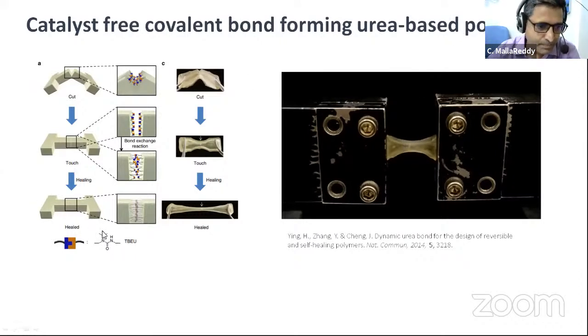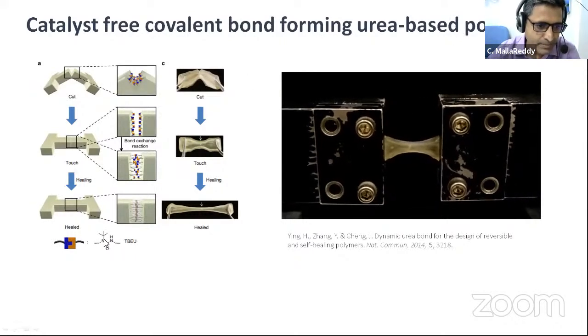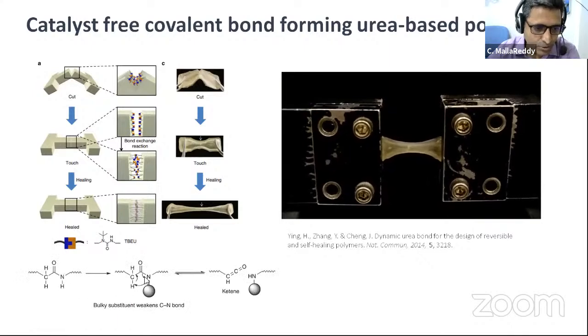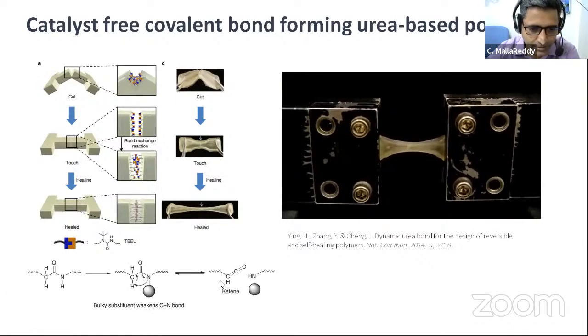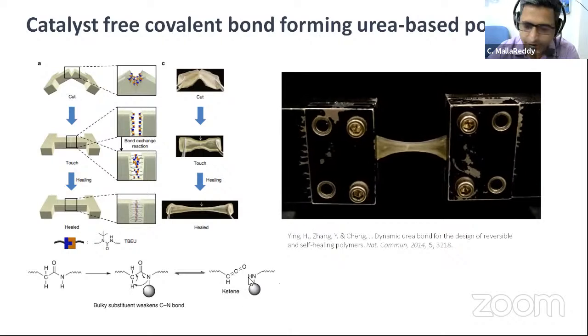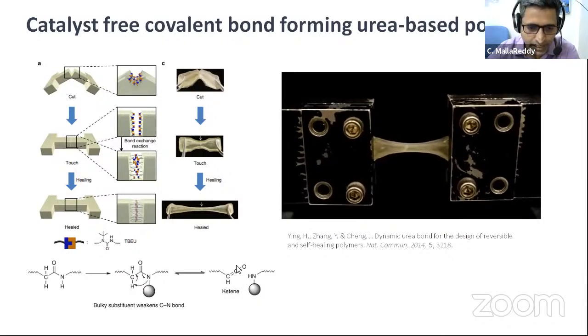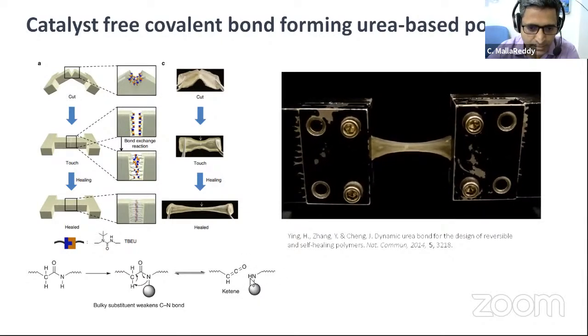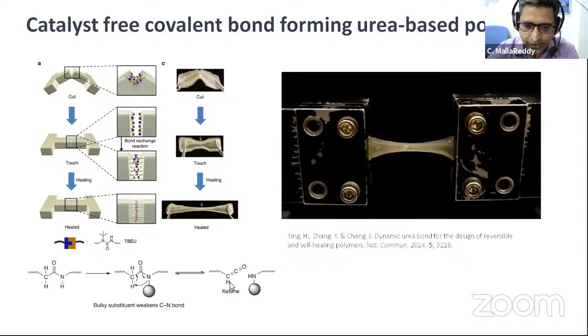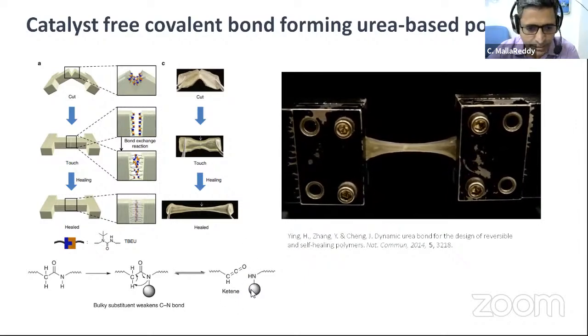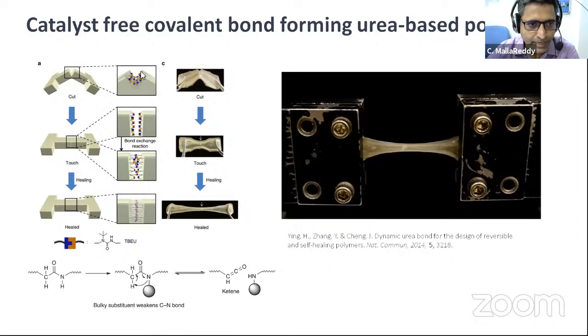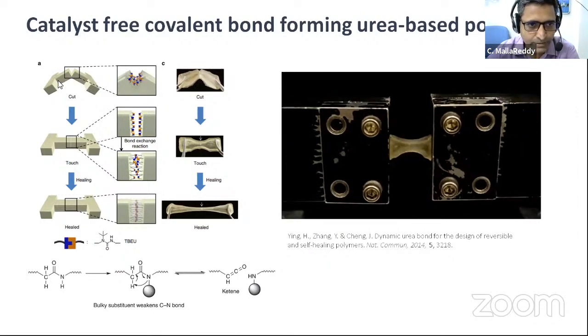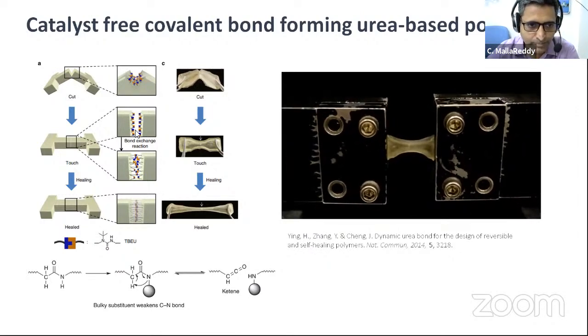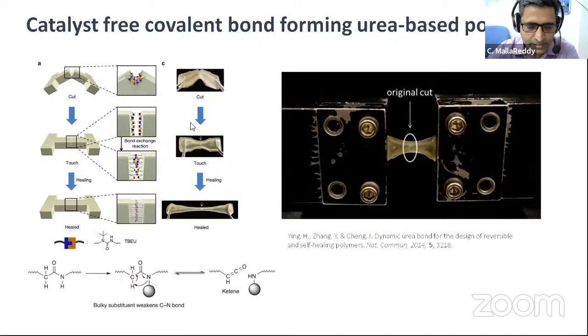If you look at here, they put a bulky group, and then this bond becomes a little weaker. And once this becomes weaker, then you basically form a ketene, and then you get an amine, and you break this covalent bond, the CN bond, and then these can react again because they are not very stable. And that is how, when you make a crack in the polymer and then put it back together again, they react, and then there is self-healing. So these are the different methods.